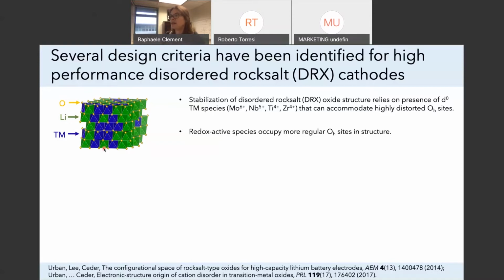And so we need some transition metal species such as molybdenum 6+, niobium 5+, titanium 4+, zirconium 4+, which have no d electrons to accommodate these distorted sites and enable redox active species, such as manganese, for instance, to occupy more regular octahedral sites. And so that stabilizes the structure.